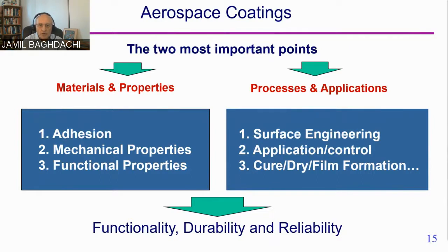So the first thing, as you know, on the material properties is adhesion. Coatings function by adhesion. Without it, forget it. It's not the beauty of it. For airplanes, we want to look for adhesion, and the mechanical properties of the coating. It should not be easily removable, but surprise, I hope you can believe me, I go to these bases often enough, with a fingernail at times, don't tell anyone, okay, I'm able to sometimes scratch it.